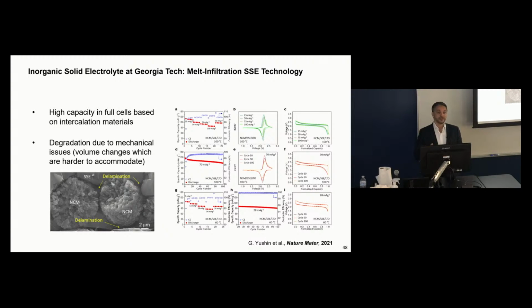So we built these full cells, and the performance was eventually quite good. We can have high capacity, we have small hysteresis, we have good overall characteristics, but we also noticed that the cell degradation does take place. And the challenge comes from the fact that, as I mentioned, all materials, even intercalation-type cathodes, they have some volume changes during cycling, right? You extract lithium from NCM, actually it swells a little bit, and it contracts a little bit.